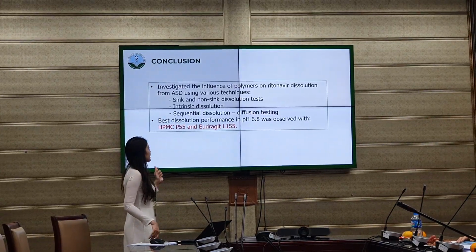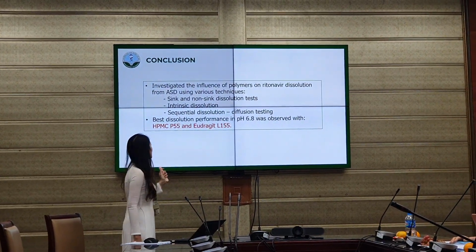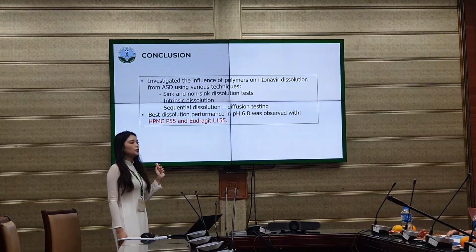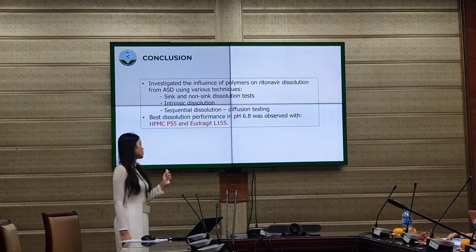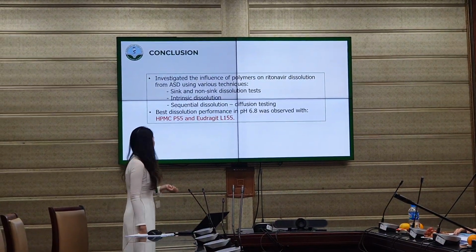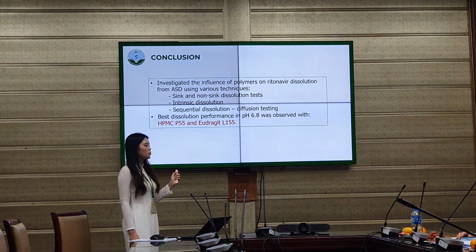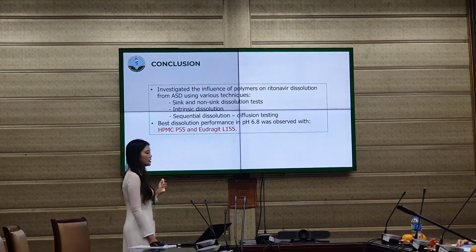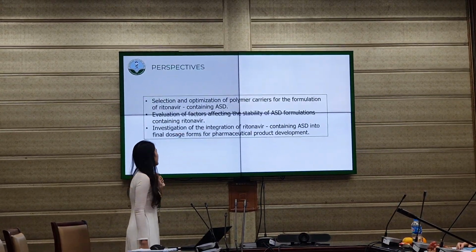We investigated the influence of polymer on ritonavir dissolution from ASD using various techniques. First, sink and non-sink dissolution tests. Next is intrinsic dissolution. And lastly is sequential dissolution diffusion testing. And the best dissolution performance in pH 6.8 was observed with HPMC P55 and Eudragit L155.